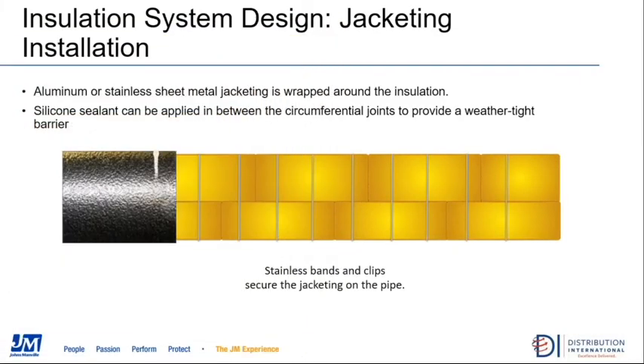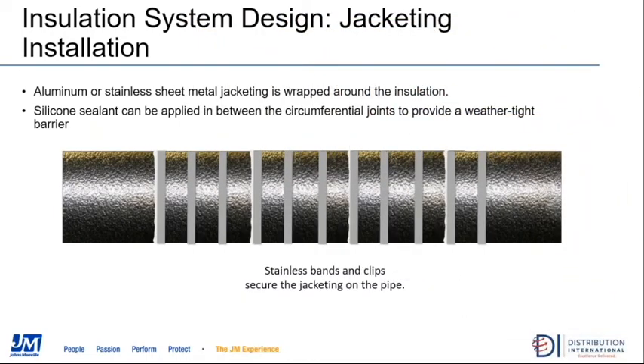The other thing is when you install your jacketing system, you want to make sure that the seam of the jacket is positioned so that water is going to shed off that jacket. Also want to make sure that the jacket is installed with all of your joints overlapping, of course, and then you want to have silicone sealant applied in between all of those seams and joints. It's going to make the system watertight. And then we want to make sure we adhere to the pipe with stainless steel bands or clips.